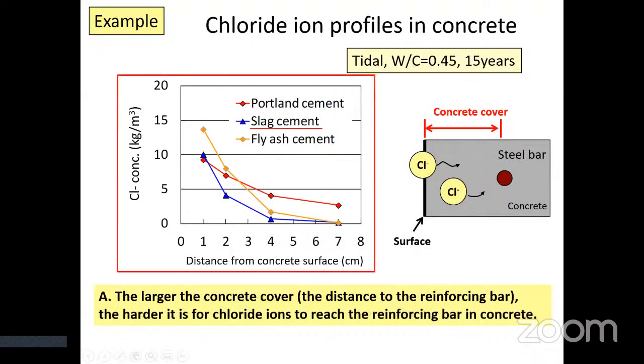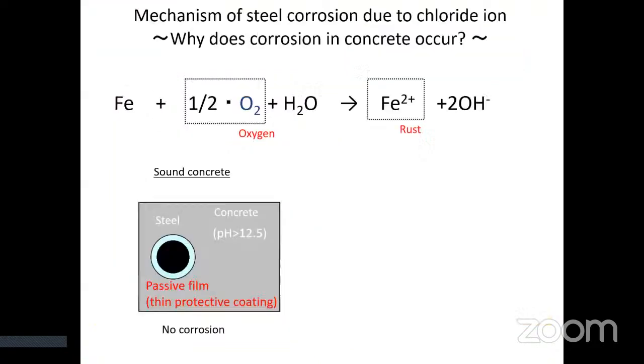This figure is an example of the chloride ion profile that penetrated into concrete after 15 years. The concentration of chloride ion is higher around the concrete surface and lower inside the concrete. That is, the larger the concrete cover, the harder it is for chloride ions to reach the rebar in concrete.